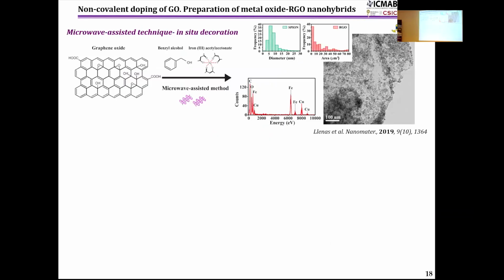Okay, so another approach that we can use for modifying the properties of the material is making non-covalent doping, in this case, by the decoration of graphene oxide or graphene derivatives with inorganic oxides. In this work, we made the modification by using an iron salt that was reduced under microwave techniques. And we were able to obtain graphene oxide decorated with SPION nanoparticles. These samples find applications in MRI.